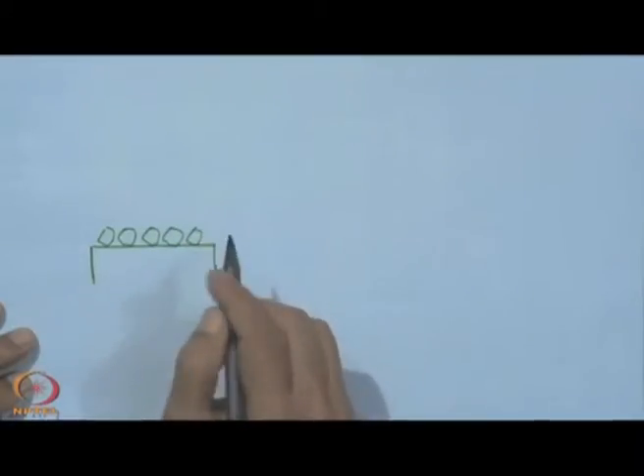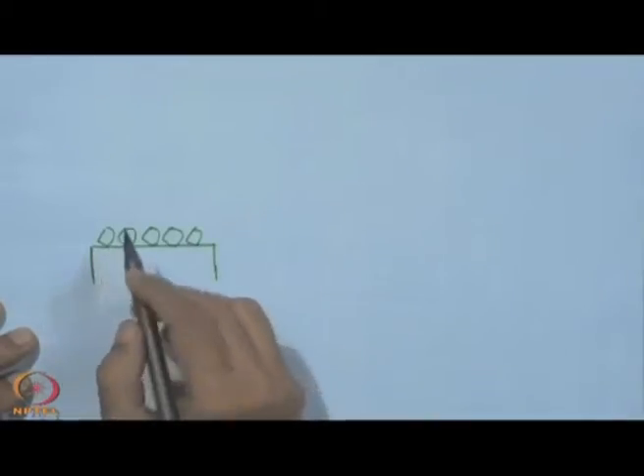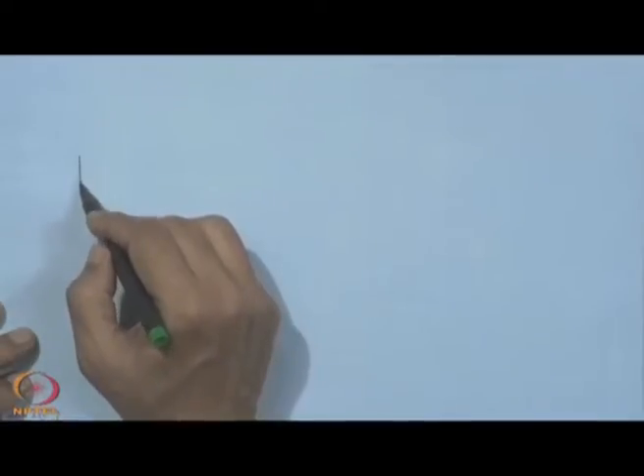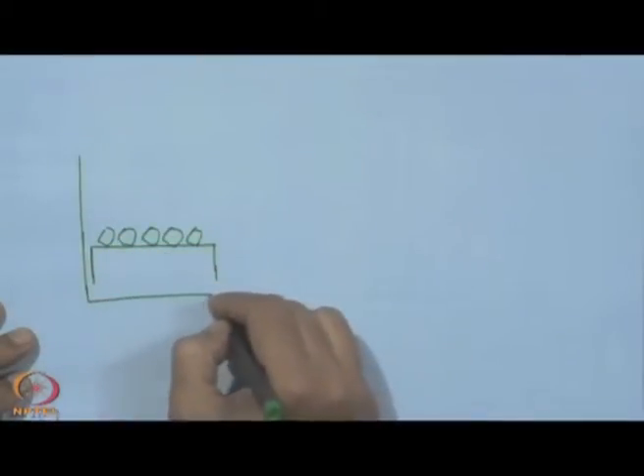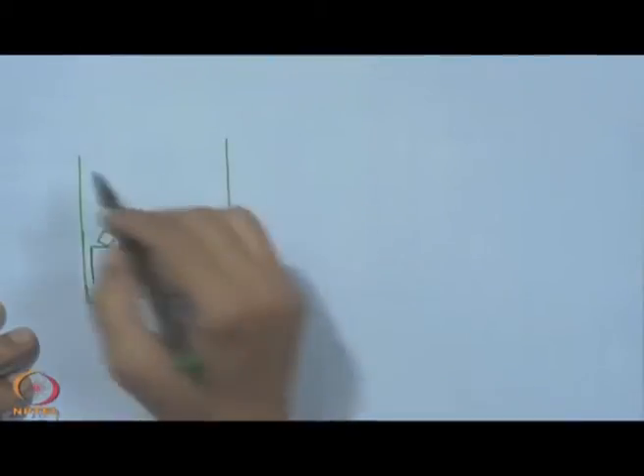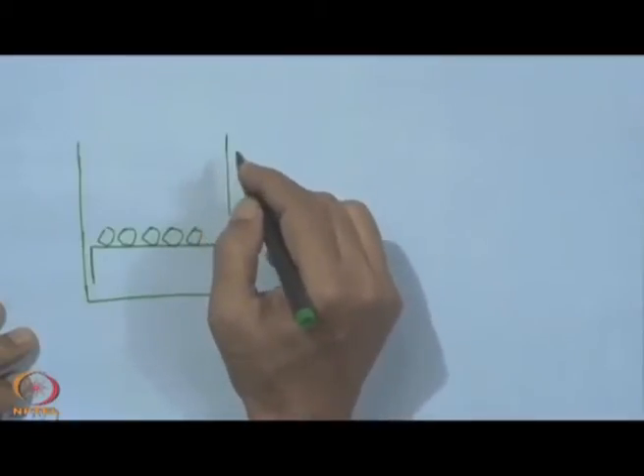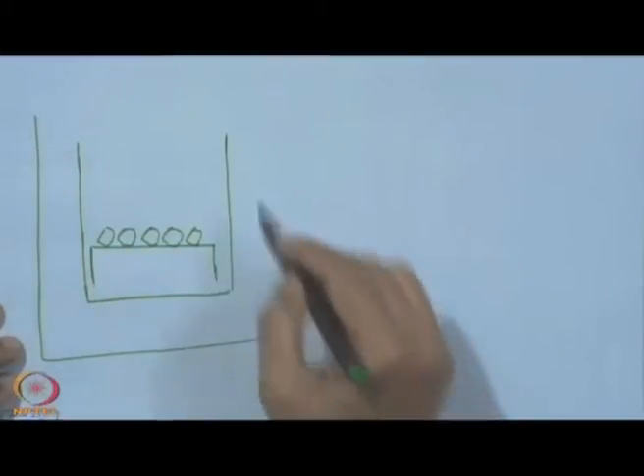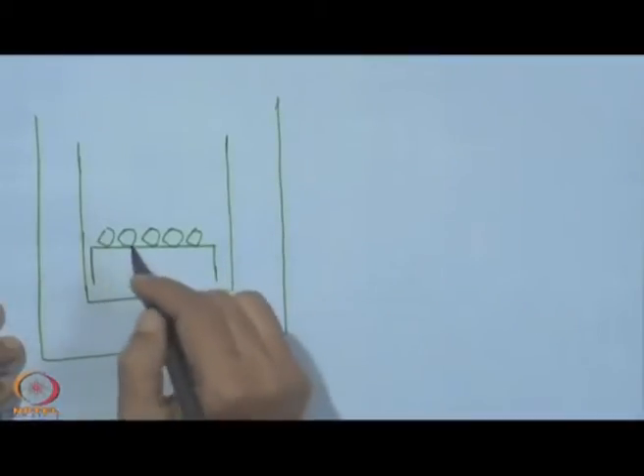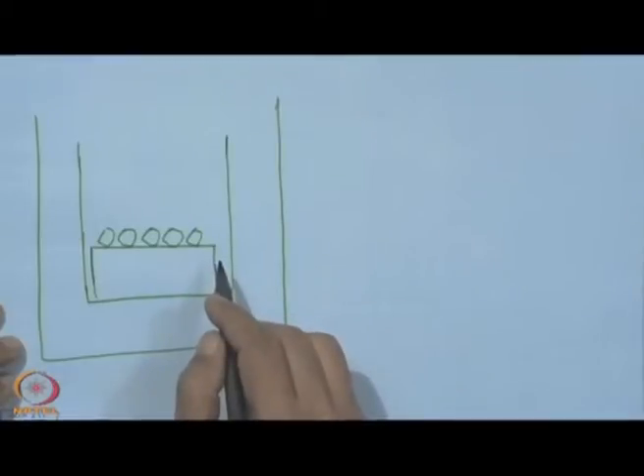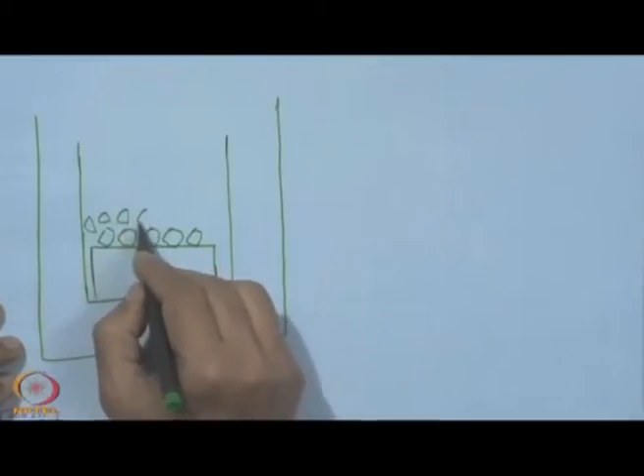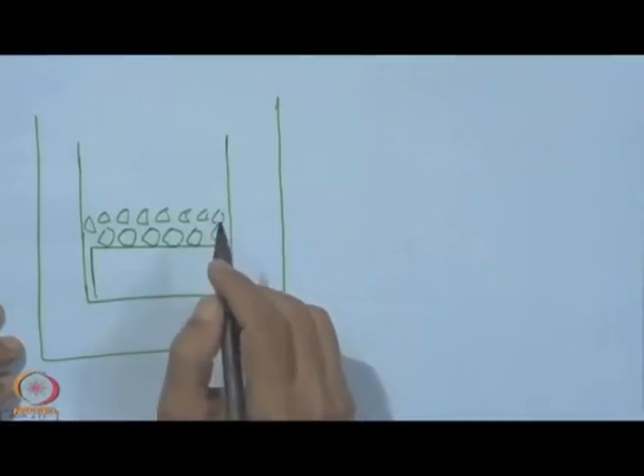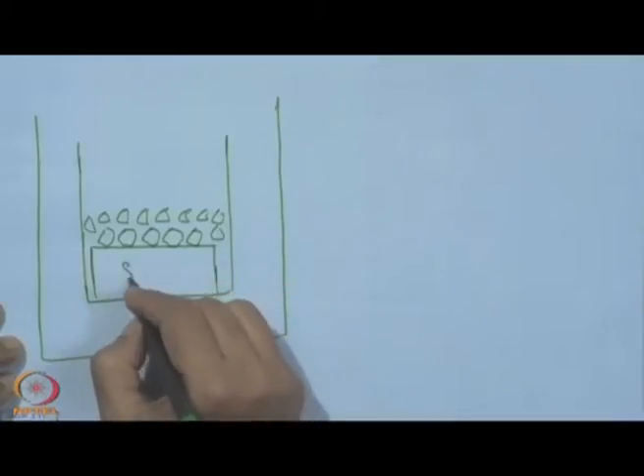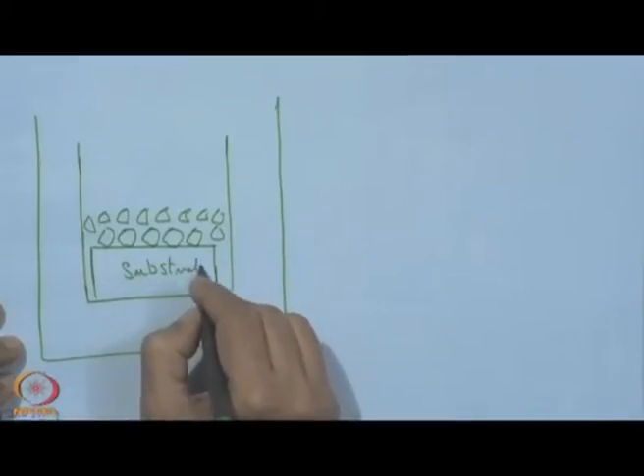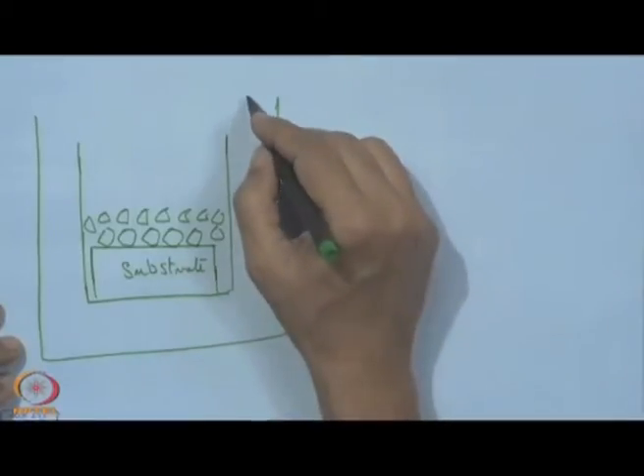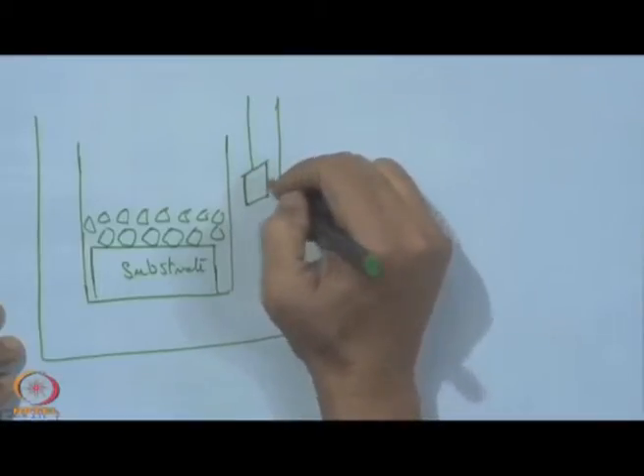What we see here are the crystals of the abrasive, and this is going to be a diamond bed. So, that means there will be a container having pores. It is almost like a strainer, and over that we have one electroplating bath, and this is submerged in this abrasive bed, and here you have a high concentration of this abrasive material. And then this substrate will act like the cathode, and we can have another plate which will be the anode.